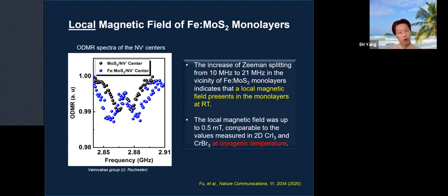Now, the local magnetic field measurement is important to show that this effect doesn't come from some average effect of surrounding materials or some residues or some leftover ions here and there. Of course, we don't have that, but assume that we have some residues. Then, if this is not a local magnetic field measurement, this is kind of an average measurement, you will pick up those things somewhere. But this local magnetic field means that this effect comes from these substituted atoms directly, okay?